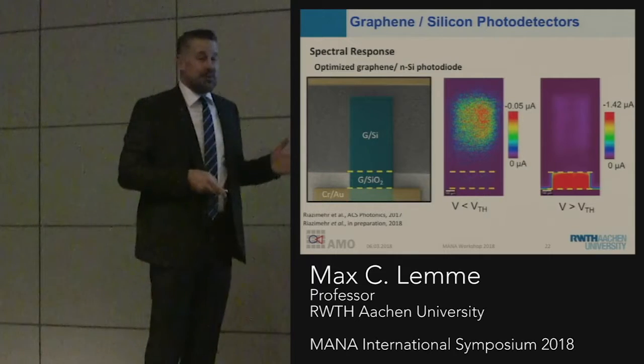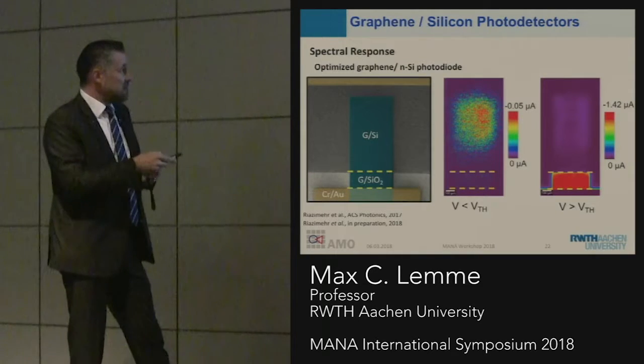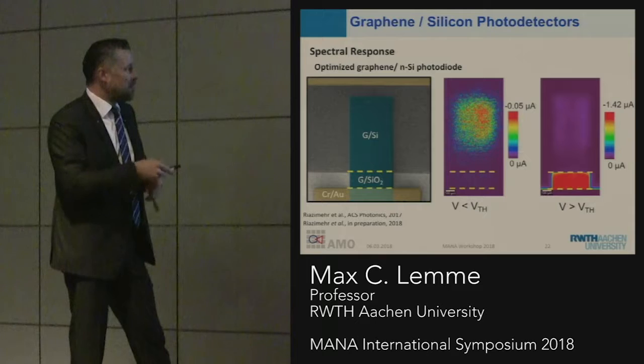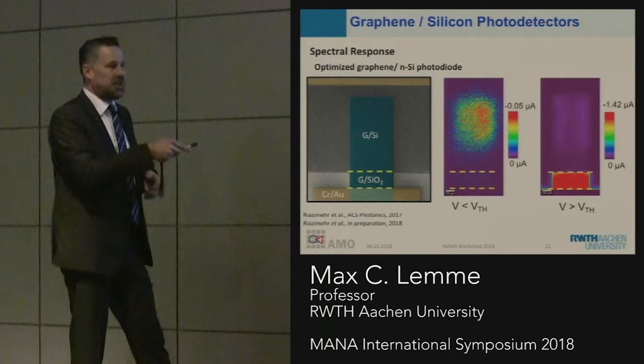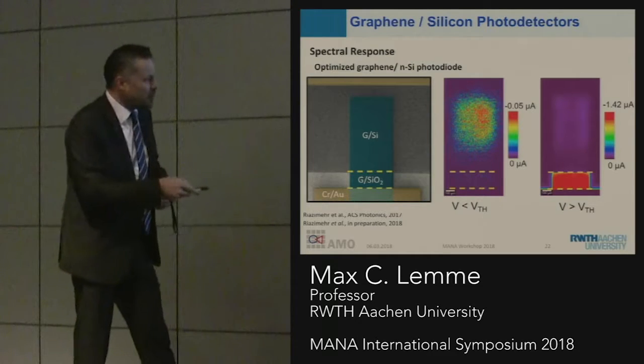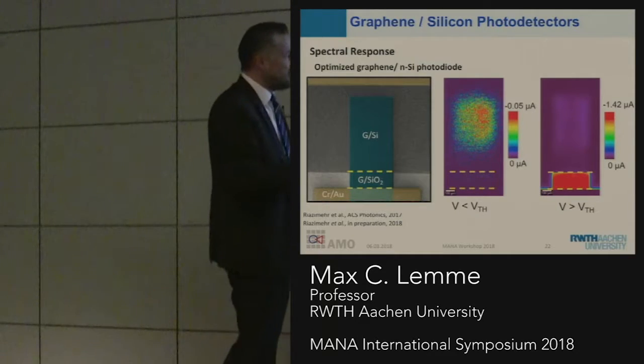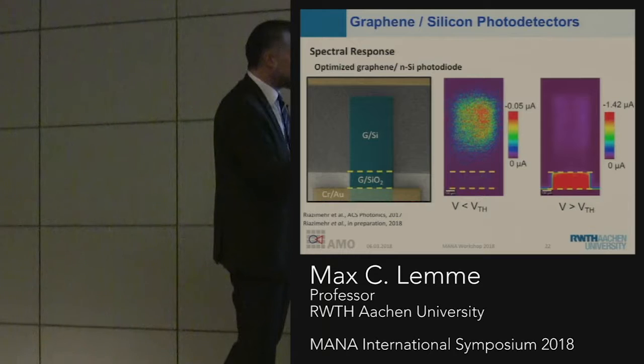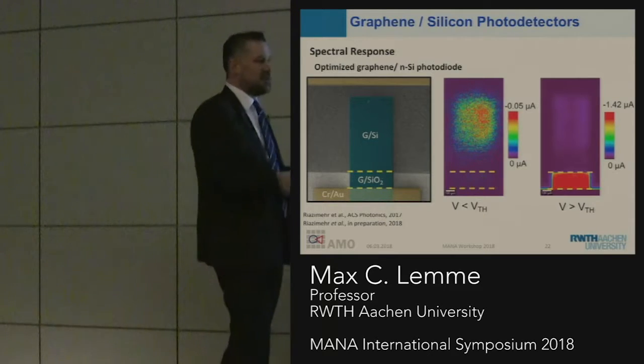Now we've looked at this in more detail, and when we do another scanning photocurrent measurement of this diode, we see that for small bias, the main photocurrent comes from the Schottky region. But if we go beyond a certain threshold voltage, the main contribution actually comes from this region here, which is on the silicon oxide.